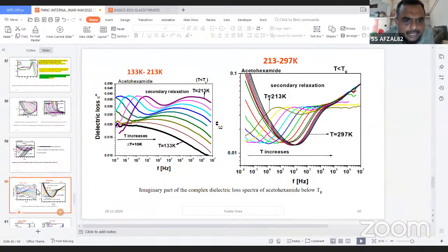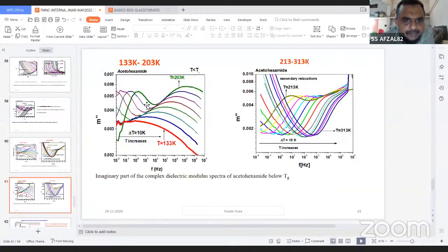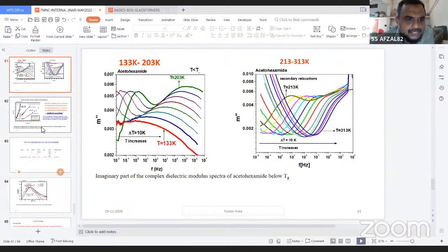See, when I plotted these things in the modulus, I am also getting similar graphs at the glassy state, because it is at the low temperature. And this is also in the glassy state, that is 313 Kelvin is below the glass transition temperature. So at the glassy state, I'm getting relaxation, which is secondary relaxation, both in the modulus representation and as well as in the dielectric representation.